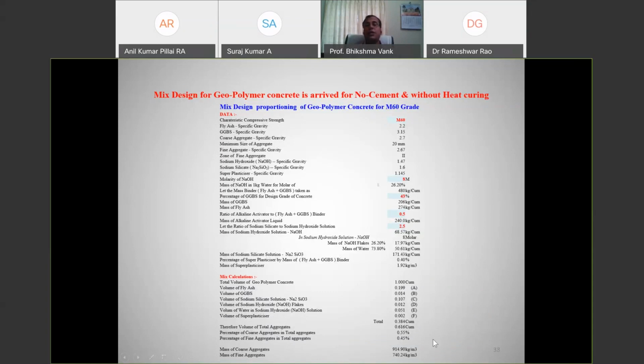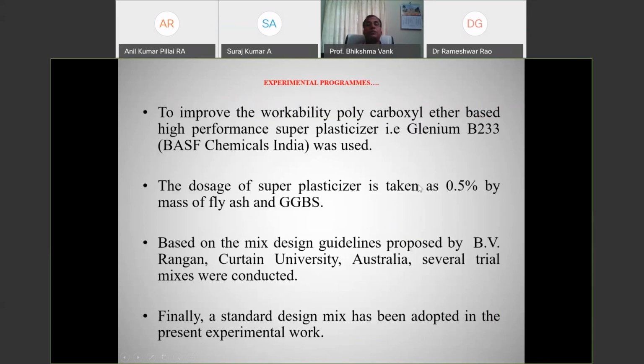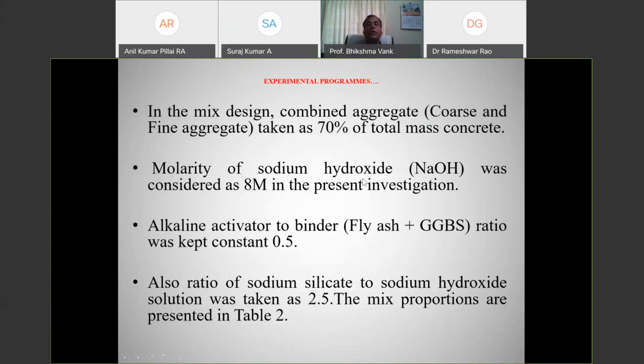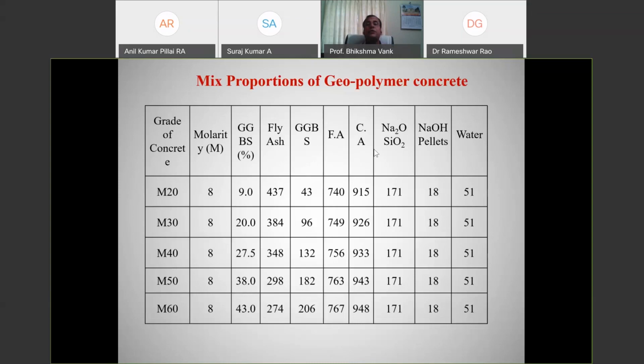All these trials have been done, and then special concrete has been made. To improve the workability, a dosage of superplasticizer has been used. All the precautions have been taken by taking 8 molarity sodium hydroxide, sodium silicate, fly ash and GGBS, and the mix proportions of geopolymer concrete were finally arrived at like this.